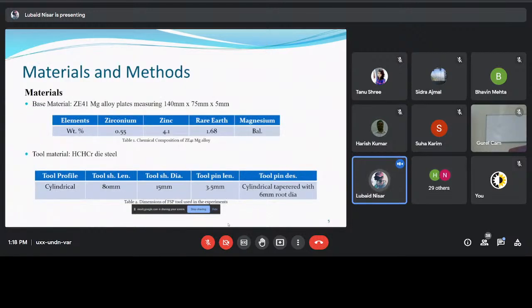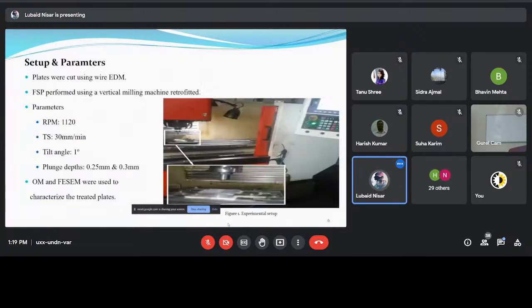Now the materials and methods. The material that we selected for carrying out this experimentation was ZE41 magnesium alloy. We used plates measuring 140 by 75 by 5 millimeters. The tool material used for this experiment was high chromium, high carbon die steel, and the dimensions of our tool are as follows. The tool profile was cylindrical. The tool shoulder length was 80 millimeters. The tool shoulder diameter was 15 millimeters. The pin length was 3.5 millimeters. And the pin profile that we used was cylindrical tapered with a 6 millimeter root diameter.